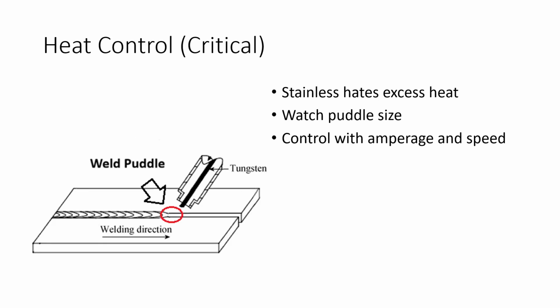Heat control. Stainless steels hate excessive heat. We can get all kinds of weird things happening if we overheat the material. So we need to watch the amount of heat we're putting in it. We need to watch the puddle size, make sure we don't get some kind of ginormous puddle. And then we need to do this, how we're going to control our heat input. We're going to control it with our amperage and our speed. Sometimes we might have to travel faster and or turn down the amperage depending on what we got going on.